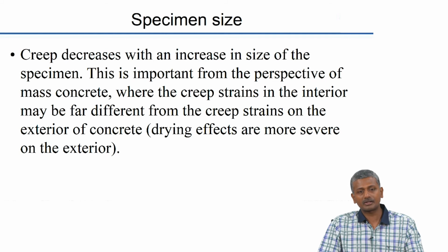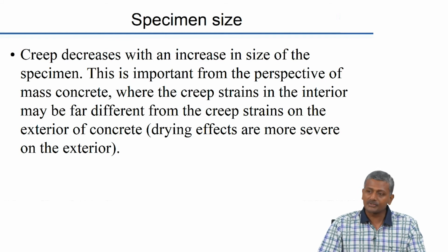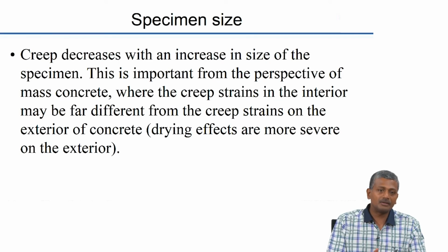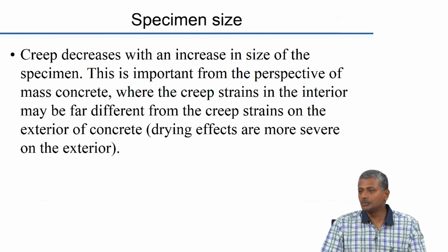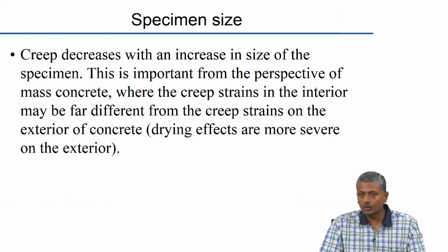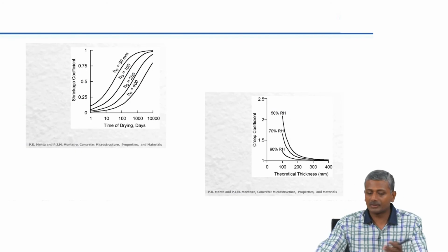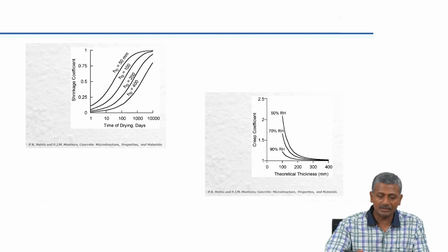Okay. So, even in large structures where the overall strains due to creep may be low, the difference in strains in the interior and exterior can lead to substantially large risks of cracking because of creep. In smaller structures you will have almost an equal rate of creep throughout the cross section of the structure. Okay. But then the extent of creep that happens in smaller structures will be much greater than the extent of creep in larger specimens.